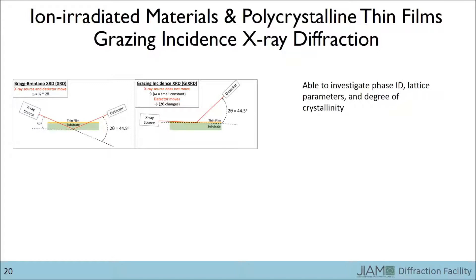With knowledge of the expected composition and density of your material, however, we can estimate the penetration depth of the X-rays as a function of omega, which is the angle at which the X-rays strike your sample. This helps to ensure that you only study the depth of your sample that is most interesting to you.